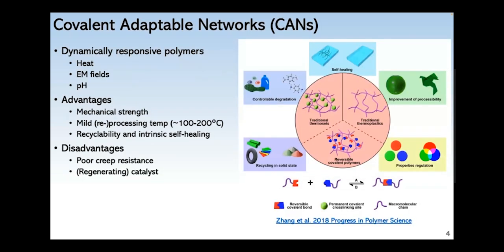Diels-Alder thermosets fall into the broader family of covalent adaptable networks, which are dynamically responsive polymers that change their topology and properties significantly with a stimulus like heat, electromagnetic fields, and pH. Their general advantages include their high mechanical strength and chemical and scratch resistance, like a conventional thermoset with permanent bonding. But unlike a conventional thermoset, the CANs have reverse processes, which become active at relatively mild temperatures, say from 100 to 200 C, at which you can reprocess these materials. And this dynamic equilibrium between the forward and reverse processes allows for the recyclability and for their intrinsic self-healing properties.